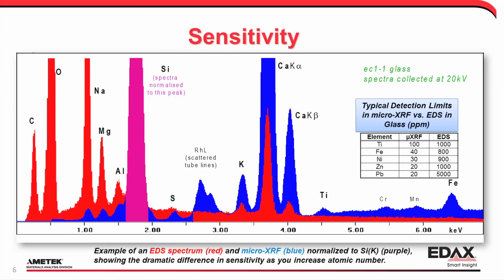So in the earlier part of the spectrum, you see carbon, oxygen, sodium, magnesium, aluminum coming in very strong with EDS. They start to kind of even out at a certain point, and then beyond that point, you're seeing elements with micro-XRF that you don't detect with an electron beam, like chrome, manganese, and iron. Sorry, that's covering that little top a little bit, but the sensitivities or the detection limits for each technique, for micro-XRF and for EDS, are shown for some of those elements from titanium to lead. And as you see, it gets better as you increase the atomic number with XRF.